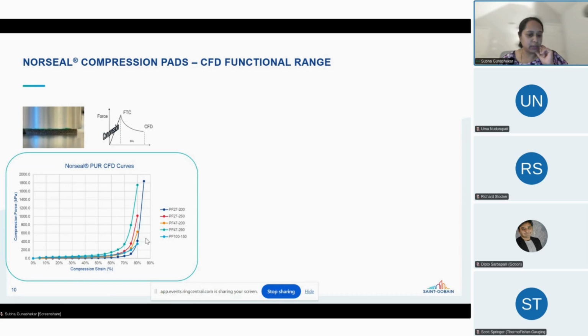Depending on the density, you can see the compression force response here. So more rigid foam will have a higher force value compared to a much softer foam. Overall, in battery cell and pack applications, what we want is to have a flatter curve over a long strain period. For example, between 10 to 60% or 10 to 70%, you don't want your force values to go up too much.